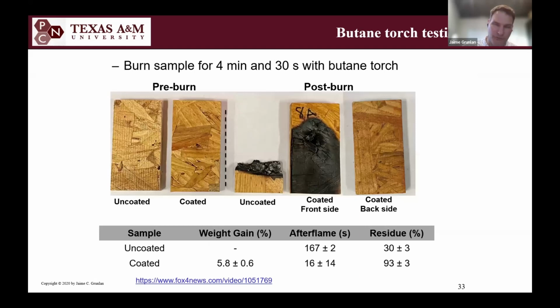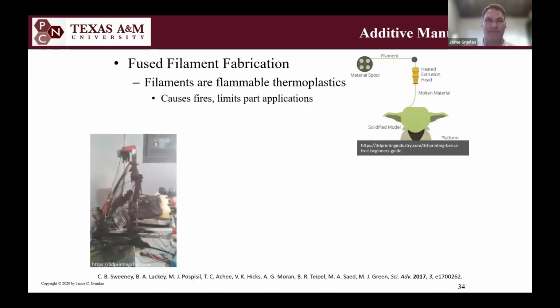And then we held a torch for 4.5 minutes. That's a weird amount of time. The reason it was 4.5 minutes is because that's how long it took for the uncoated sample to completely burn up. But the coated sample, and by the way, you can see we only added less than 6 weight% flame retardant to the coated wood, had the torch held there for 4.5 minutes. If you flip that, I think the thickness was 1/4 inch, you couldn't tell there was any fire on the front side after 4.5 minutes. So it really did a terrific job of arresting the damage and stopping the fire from spreading on that wood. So that was pretty exciting.